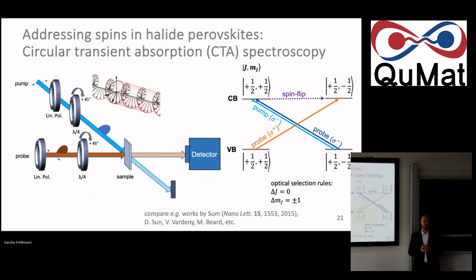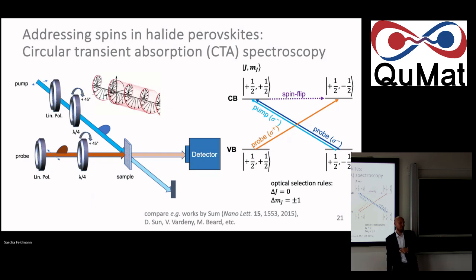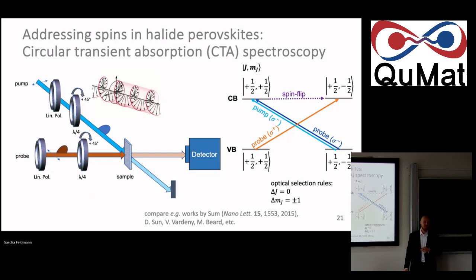at right, and that's co-polarized, would simply retrieve a normal transient absorption measurement where you create an excited state, and then you can read out how long that's alive. So if you look at the ground state here that is bleached, you will find that after some time it's less bleached. But what we can also, of course, do is excite this one state with a left-handed pulse, say, but then read out this other state with a right-handed circular polarized pulse.